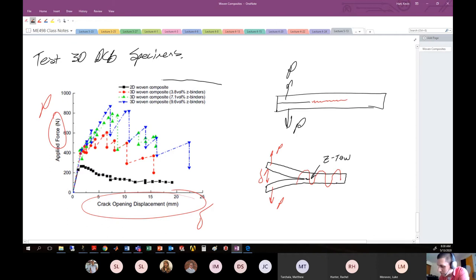Now let's look at what happens when we start to incorporate the Z-binders, the through thickness tows. And here we're incorporating them at various volume fractions. So 3.8, 7.1, or 9.6% volume fraction, that's just more or less the density of the Z-tows in the fabric. What you'll see is if you have a lot of Z-binders, so here let's look at this blue guy that has 9.6% volume fraction Z-binders, what happens? You load this guy, you load this guy, you load this guy. So here we are with loading. And all of a sudden, we get pinned at a location where we're stuck on a Z-tow. Building energy, and then all of a sudden, bang, it just releases all of that energy. And it's a massive amount of energy compared to what you would see in the 2D case.